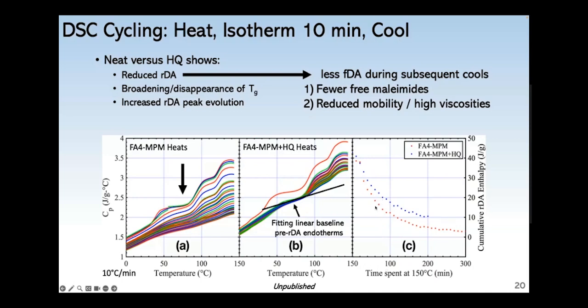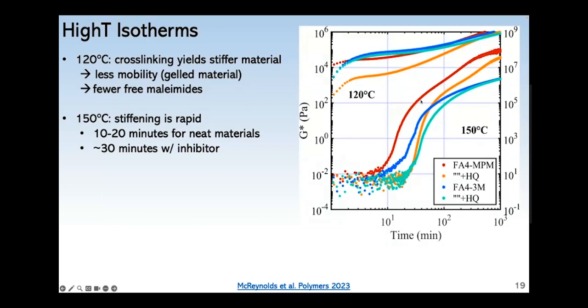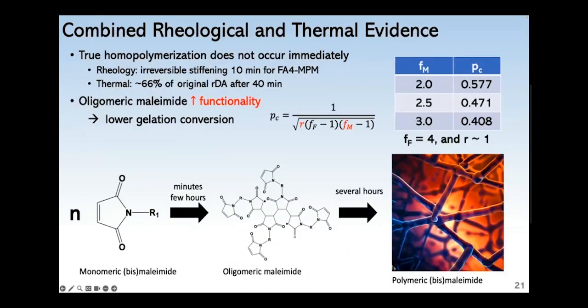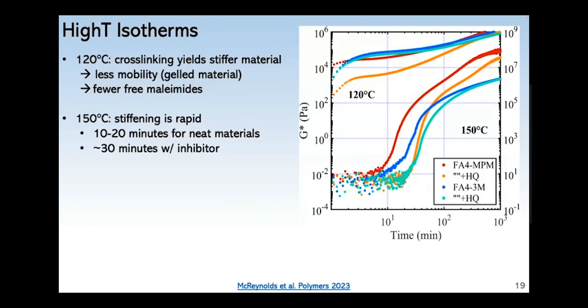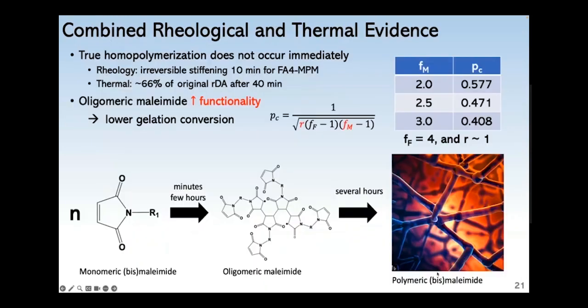Another important observation was that after about 40 minutes, there was still about 2/3 of the original RDA enthalpy. But if we go back to the last slide, at 40 minutes, the materials had significantly stiffened by that point. So what that combined evidence suggested to me is that the true homopolymerization of maleimides doesn't occur for the first couple hours. And instead, what has probably happened is that these monomeric bismaleimide molecules have made these small oligomeric structures, which have several maleimide groups on them. And as that happens, the average functionality for the maleimide increases, which pushes the critical gelation conversion down. And so I think at some of those last rheology results, these have actually undergone gelation and not formed a true maleimide network or polymeric bismaleimide.